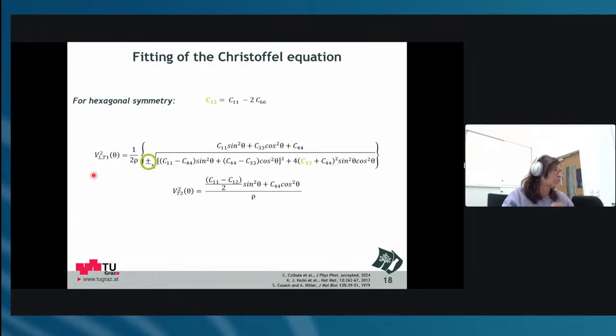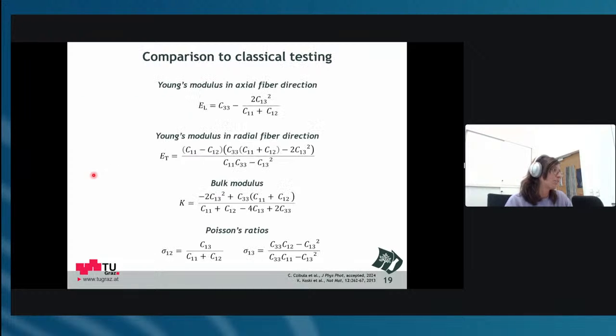When you know all those C's, you can determine your mechanical parameters as you know it from testing, because they are all in relation to each other. From that, you can get the Young's modulus in axial fiber direction, in radial fiber direction. You can get the bulk modulus, and you can get your Poisson's ratios. But you need really every C from the stiffness tensor to calculate these relations. And then ideally you can compare it to your classical mechanical testing that you have been doing.